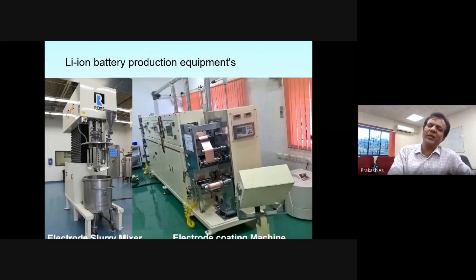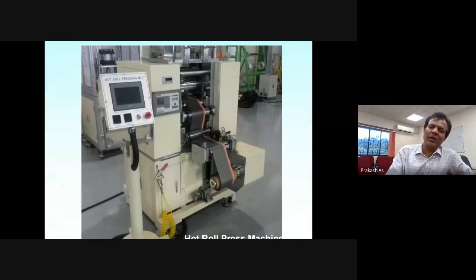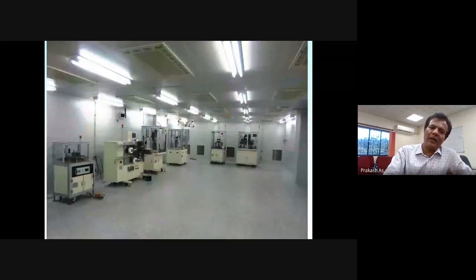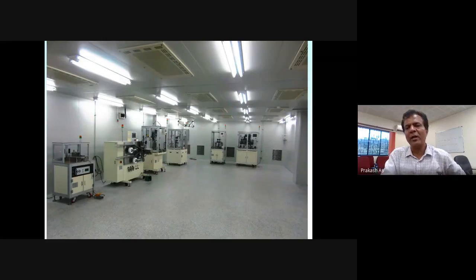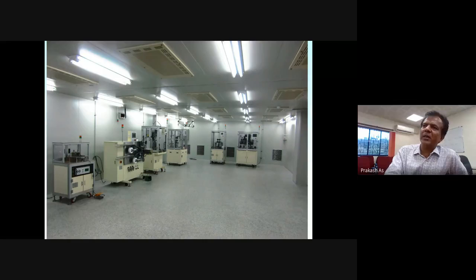And then this is called a calendering process. In this process, to get the required energy densities, the electrodes have to be compacted. The higher the compaction, the better the energy density you can get. It is a kind of compaction with heat, and then the whole battery has to be fabricated in a controlled atmosphere. The electrode materials and electrolyte are very sensitive to moisture. The atmospheric level we need is that we have to fabricate this whole battery at minus 60 degree dew point or less than 0.4% humidity level.